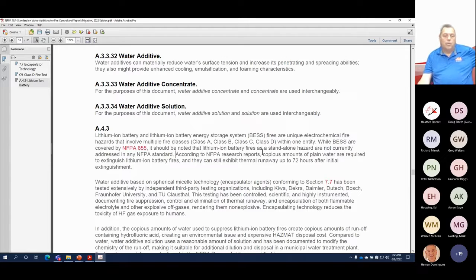So according to the research reports, copious amounts of plain water are required to extinguish lithium-ion battery fires. And they can still have thermal runaway up to 72 hours later. Now, water additives based on spherical micelle technologies, encapsulator agent conforming to section 7.7, have been extensively tested by independent third-party testing. Kiwa, I showed you that. Dekra, I showed you that. Daimler, I showed you that. Bosch, I did not show you that. Fraunhofer University and TU Clausthal, you saw that.